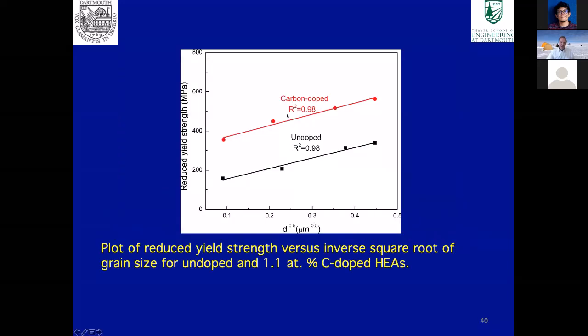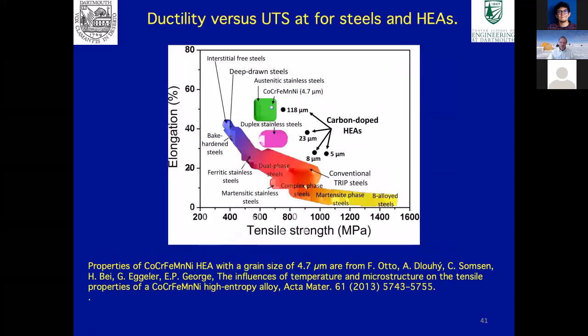So if we replot the yield strength as this reduced yield strength, where we take into account the precipitation and the change in carbides, and plot that as a function of grain size to the -1/2, you can see now the whole Hall-Petch relationship looks pretty similar for the two. And so the carbon doping doesn't do a lot to the Hall-Petch relationship.